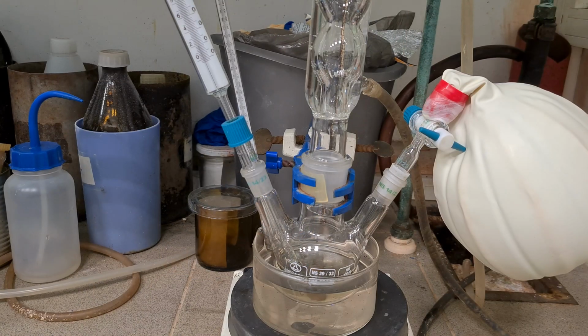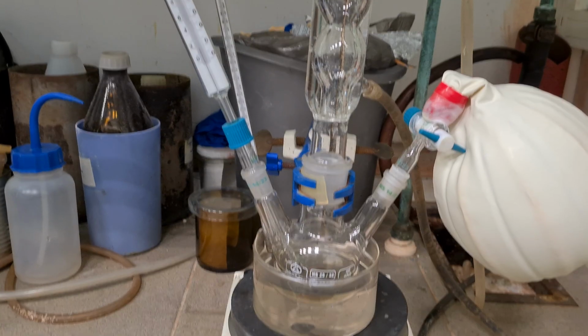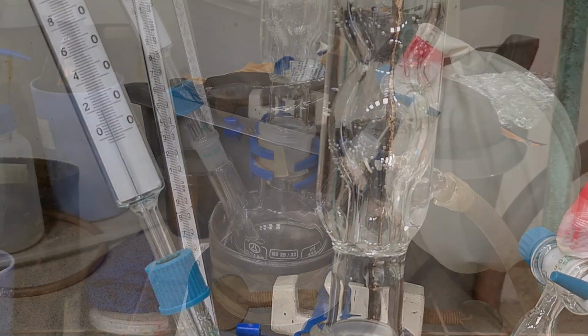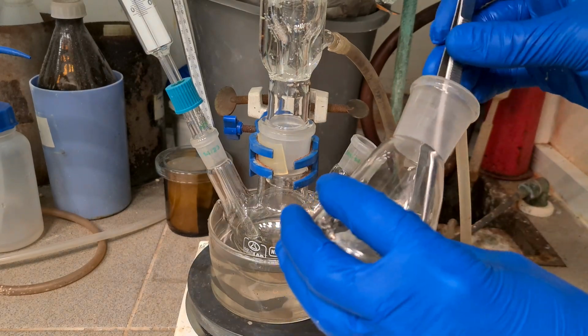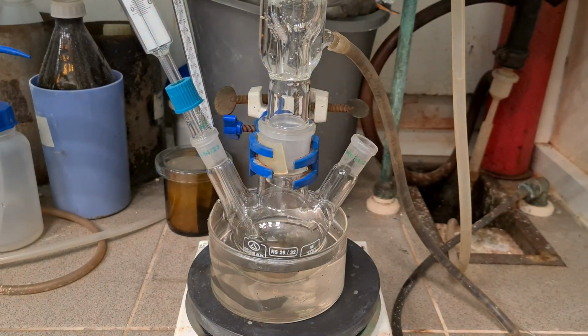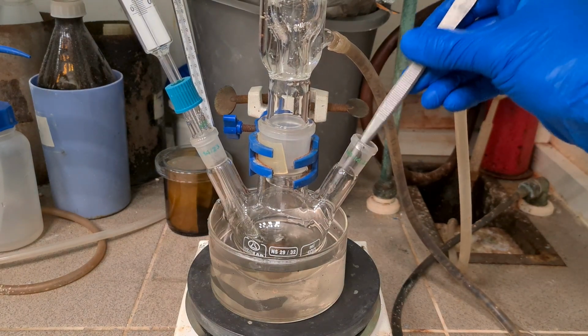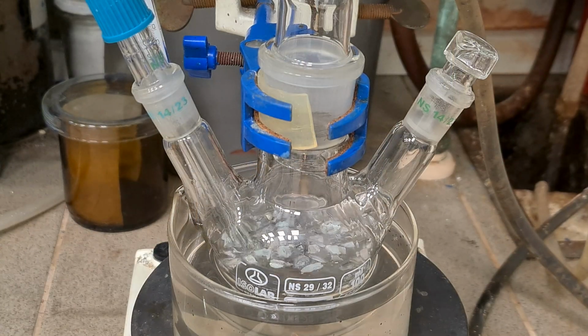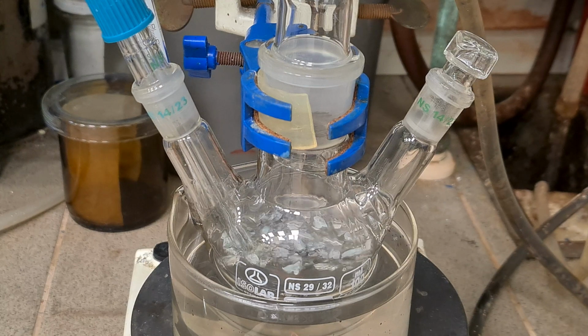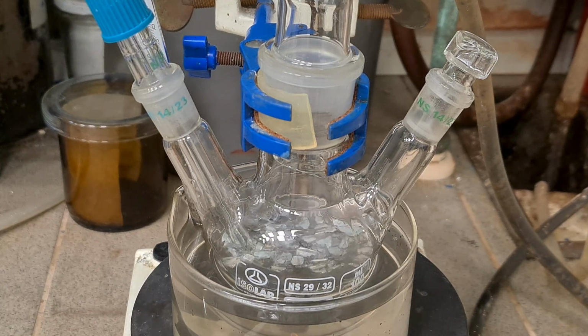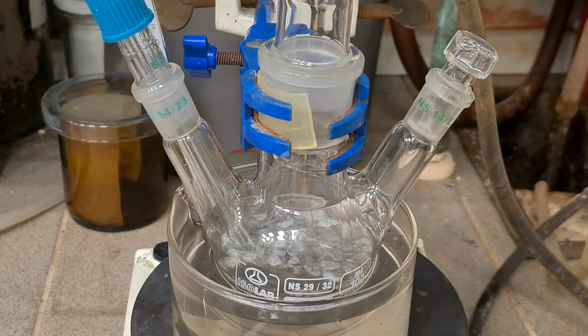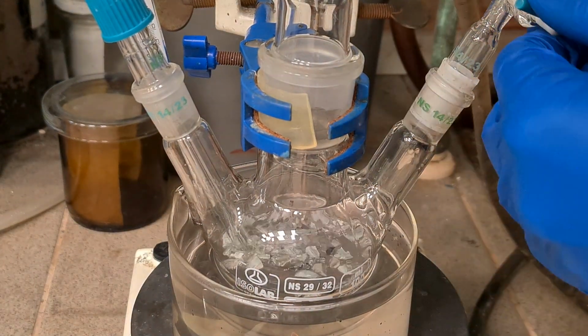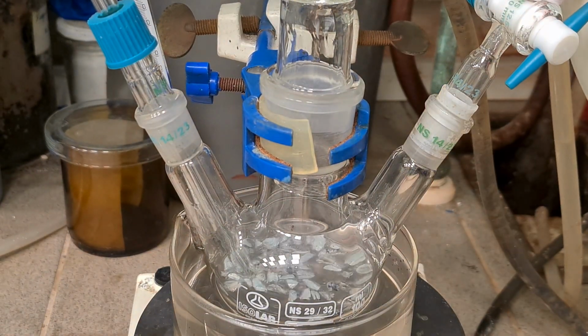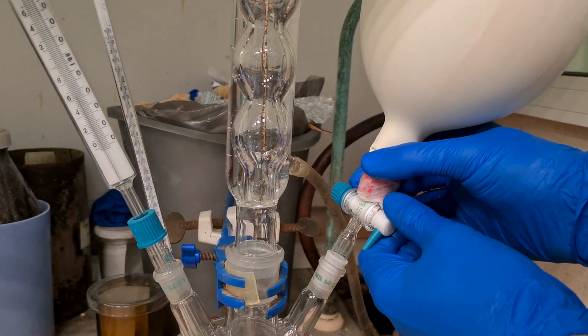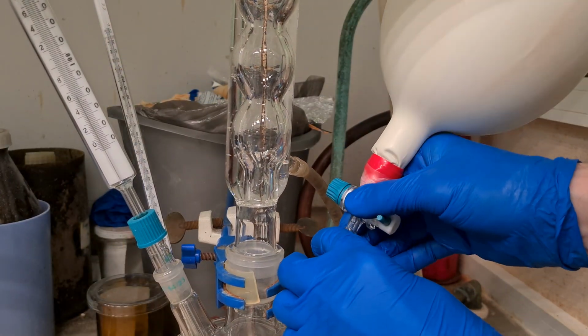Now put the whole construction into an oil bath, controlling the temperature, then put all lithium pieces into it as quickly as possible. The reaction becomes intensive at reflux conditions, 66 degrees C, releasing hydrogen gas. After THF starts boiling, purge the system with argon one additional time. Then close it with a stopper for 3 hours.